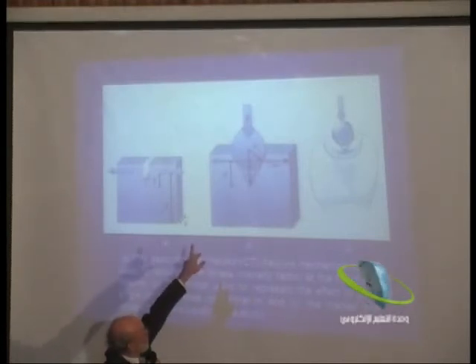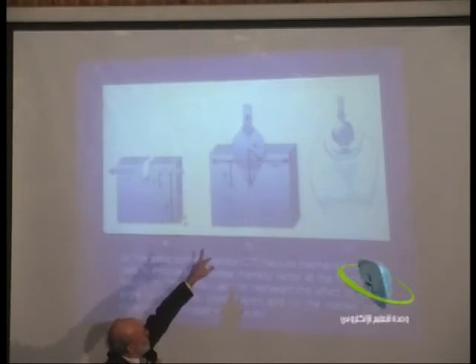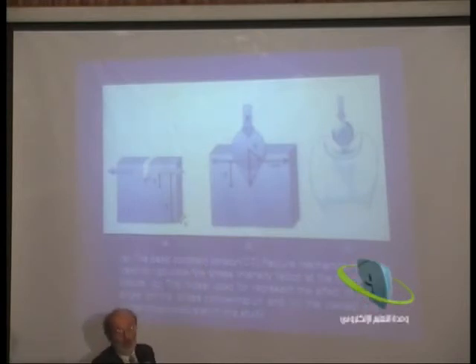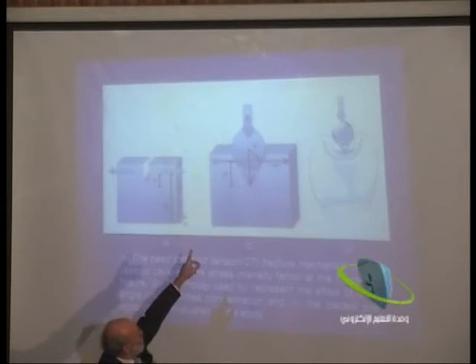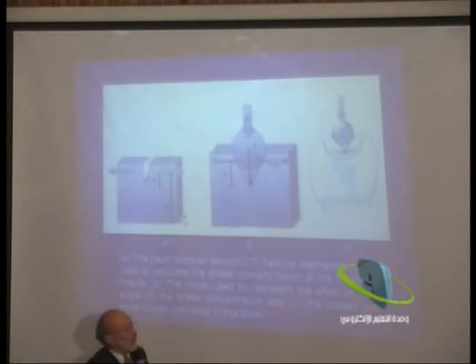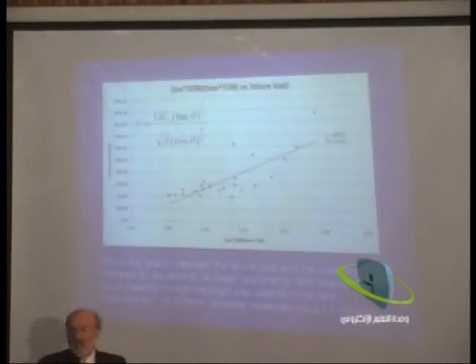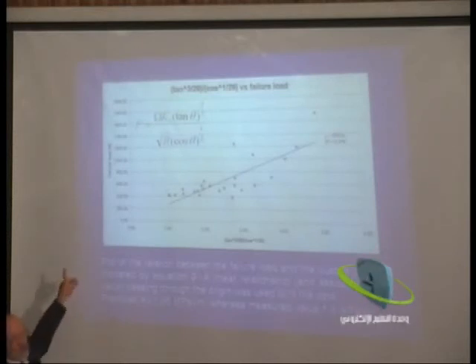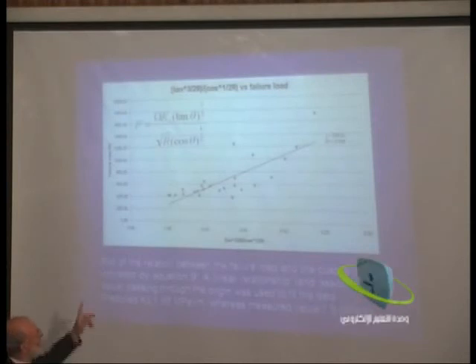We have a ball or a cylinder that's loading. We could determine from the radius and the angle of the occlusal system where the system was loaded. So we have the crack dimensions. We could know from the force and this resolution of forces what the horizontal component of that stress was. And so we could then use this simple model to reinterpret this process. And so this now enabled us to determine a relationship between the critical load, the fracture toughness of the material, the angle of the system, and the radius of the system that we loaded it with. And this is the fit that we get to that process.